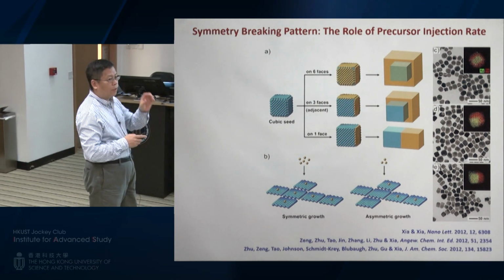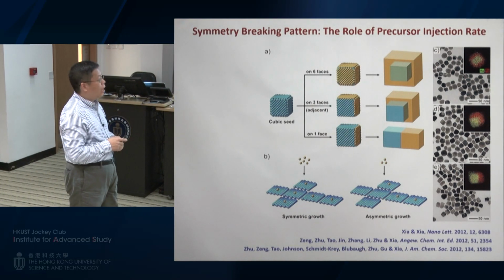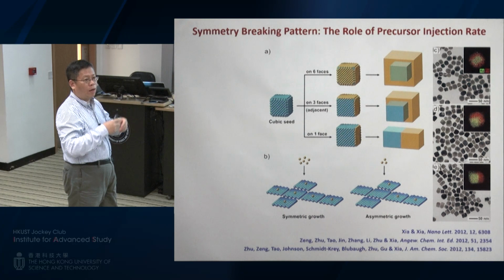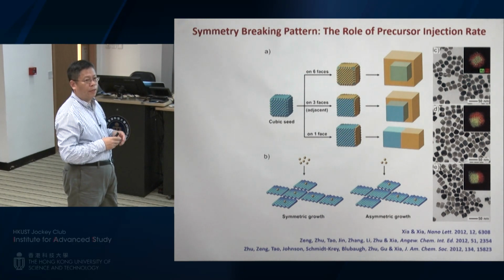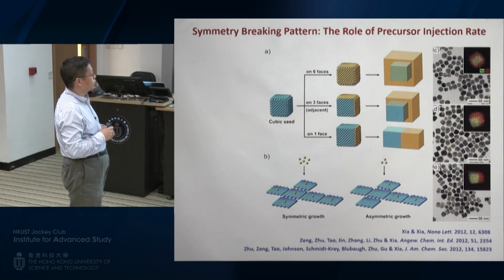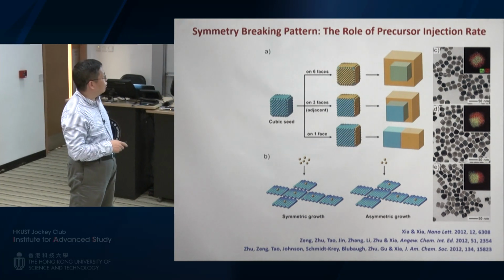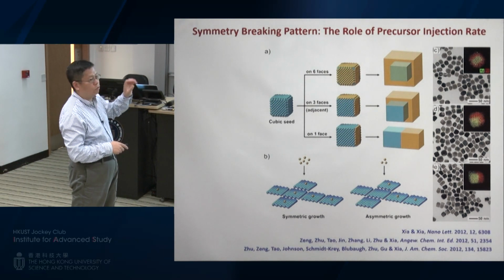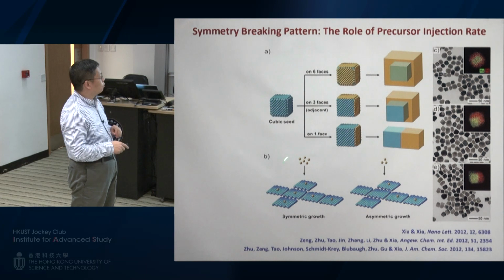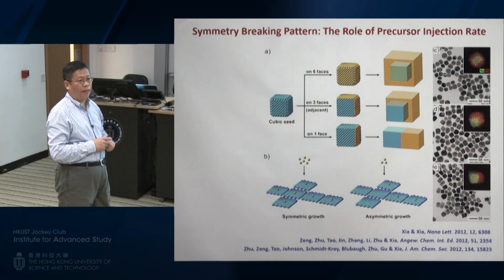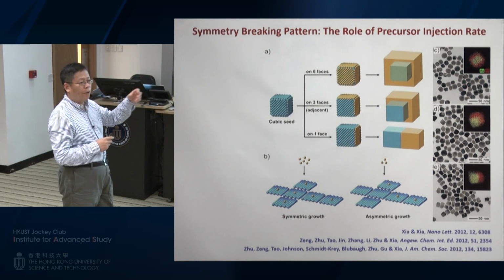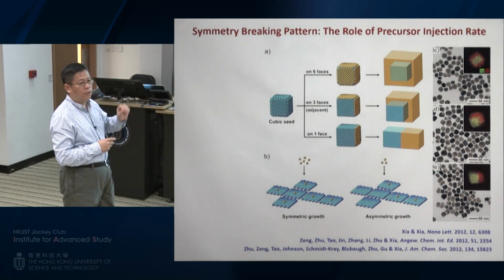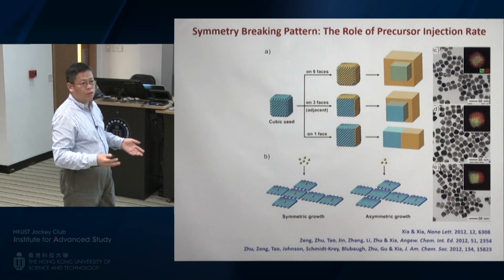It turned out to be related to the very beginning of the seeded growth. When we do seeded growth, we typically use drop-wise addition of precursor because you don't want additional nucleation events. So you always add it droplet by droplet so you can keep the concentration of precursor in the system very low. So in this case, in the very early stage, if you only add one drop or two drops into your system, these drops of precursor can only generate a certain number of atoms. And when you compare that to the number of seeds, including their equivalent sites, they may not be able to cover all of the equivalent sites, and then symmetry is going to be broken, right?